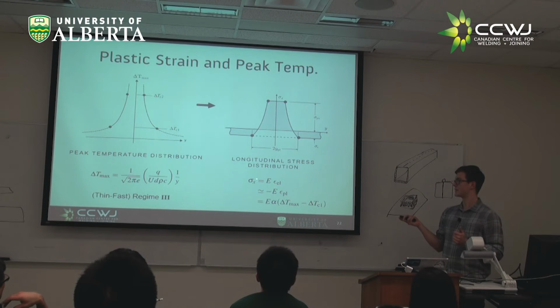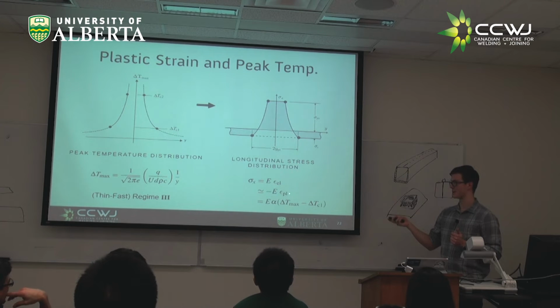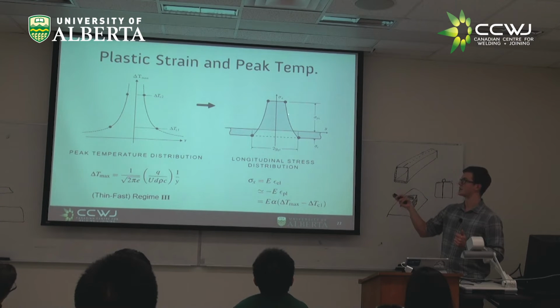And if we now look at, we said our residual stress is proportional to our elastic strain, which is proportional to our plastic strain, and our plastic strain is proportional to the difference between our maximum temperature and our delta Tc1. Really what we're saying is we get this shape, and if we want to know the total residual stress, we just have to integrate this shape.